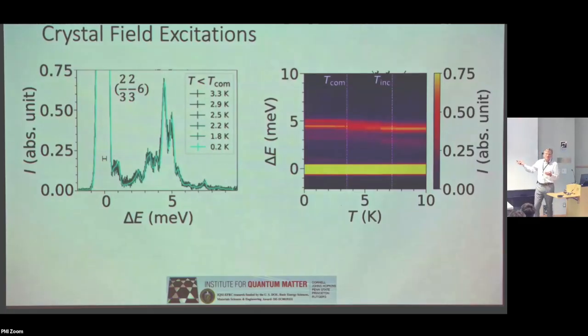But once I get into the commensurate state, then there are just two different sites that are distinguishable from each other, and they'll have their specific exchange field. And that will produce this fairly complicated pattern of multiple peaks, because there's a minority and a majority site. There's an up and two down sites, and they have different amounts of splitting observed, and there's a different number of those, and so it gets to be fairly complicated, but in a predictable way.